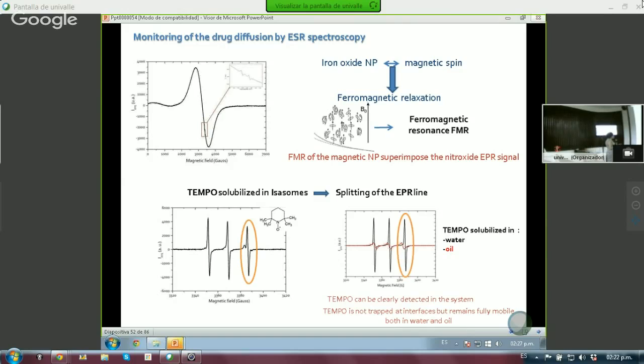So, by looking at these figures, what's the conclusion that we can draw? Well, that we can find tempo quite clearly in the system, despite the fact that we have so many components. So the tempo is clearly visible. And the second thing, if you look at the red and the blue, there isn't such a difference in the location of these peaks. The magnitude, of course, changed, but the positions are unaltered. So what does it mean? Well, it means that tempo is not trapped at the interfaces, so it moves, right? And this is what we wanted, to be able to get out of the system, but it remains fully mobile, both in water and in oil.